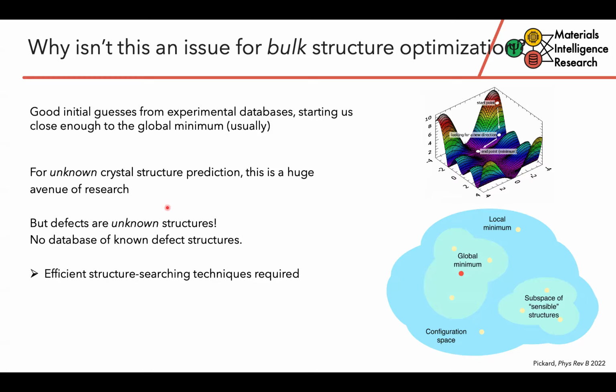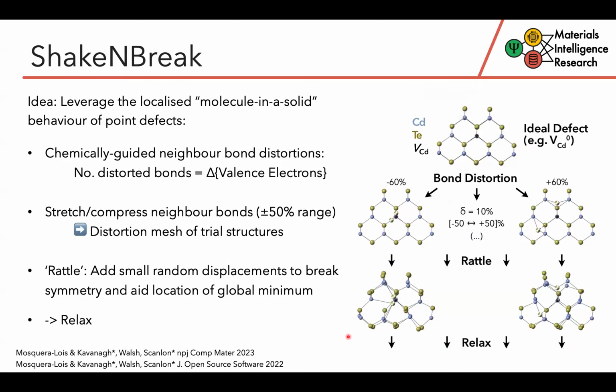And so the thing is, defects are actually unknown structures. So we have no database of known defect structures yet. And so this is essentially, I would say, the reason why these efficient structure searching techniques are required for defects. Caveat to that is that I will say that defect structures are at least a bit more constrained in terms of the configurational space than we would have with a totally brand new crystal structure. But essentially, it's the same issue of actually going into a totally unknown energy landscape. So with that in mind, at one point, I had the goal of developing a method that was both accurate and efficient in navigating this defect configuration landscape and identifying ground state and metastable defect structures. For time today, I'm going to skip over some of the core details, just so I can cover some more interesting points.